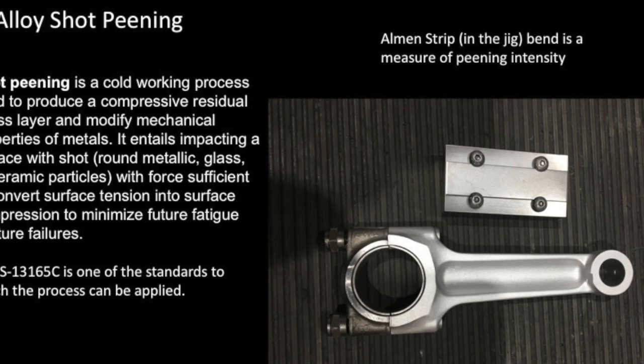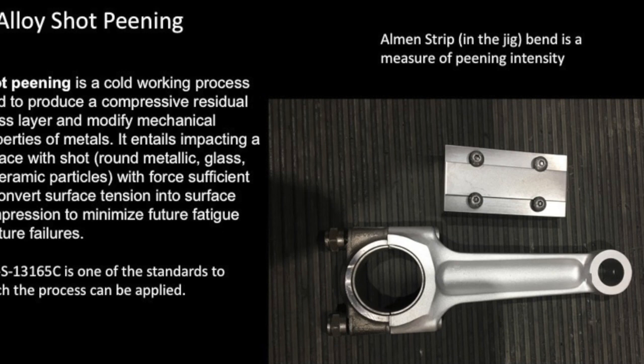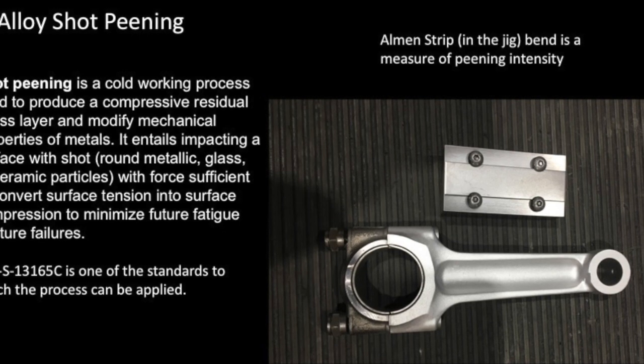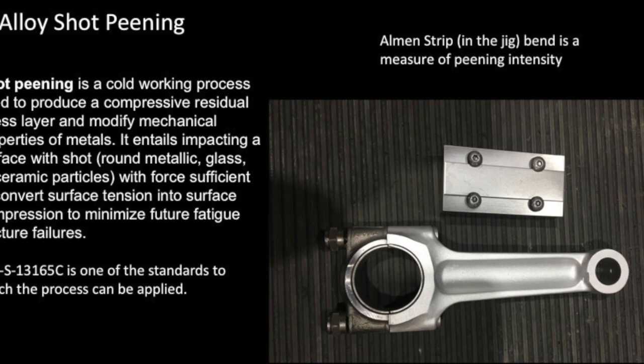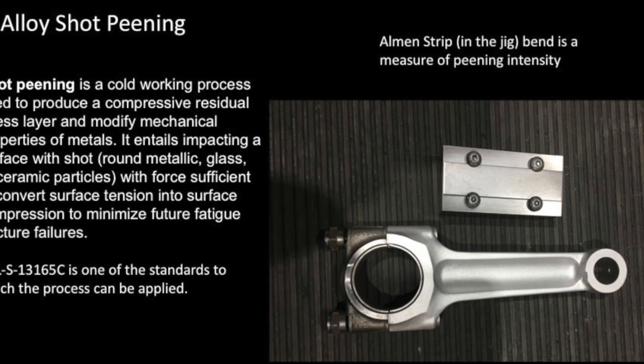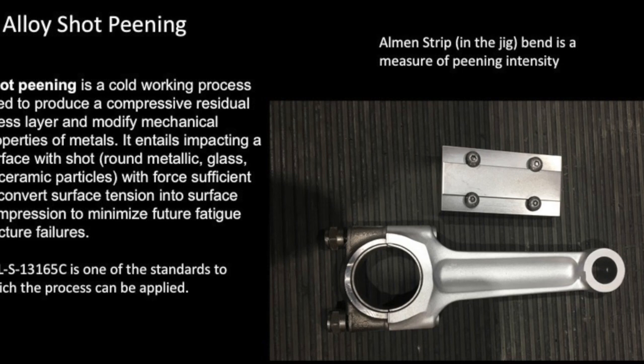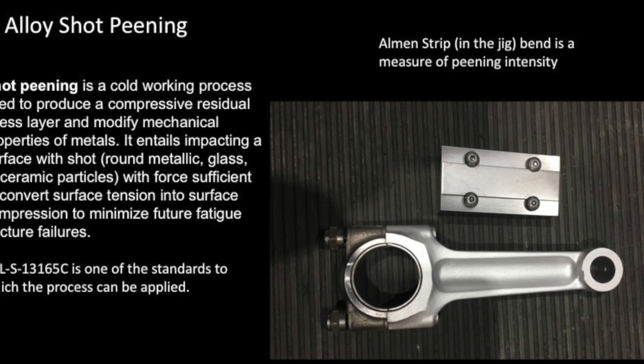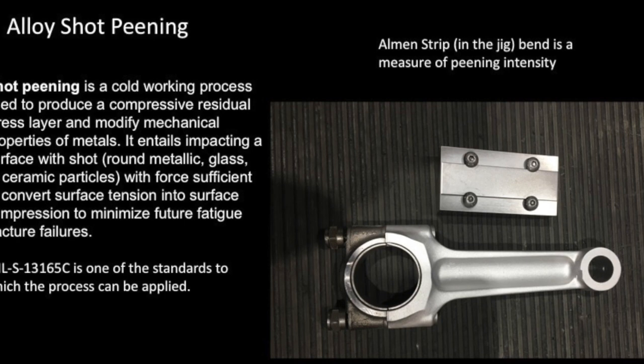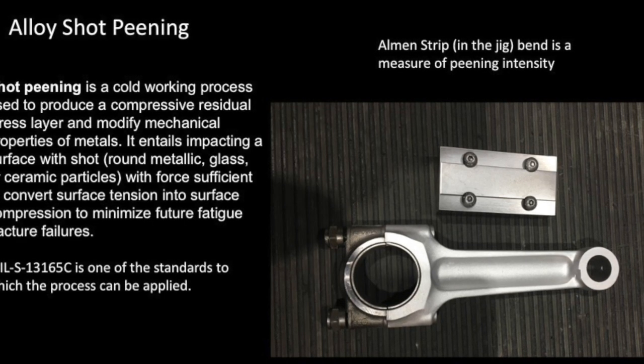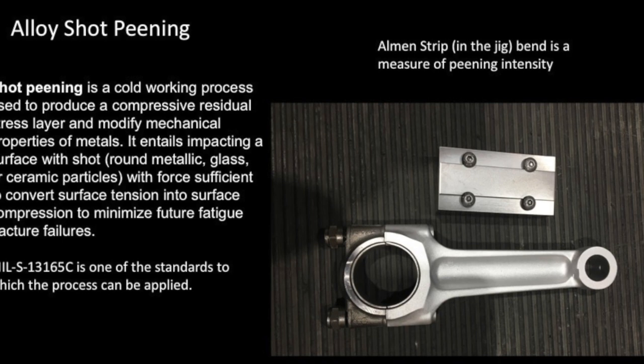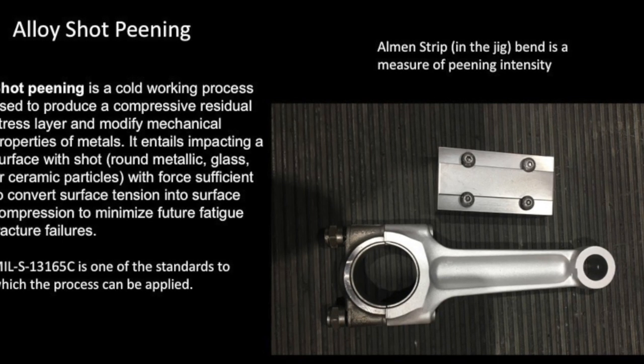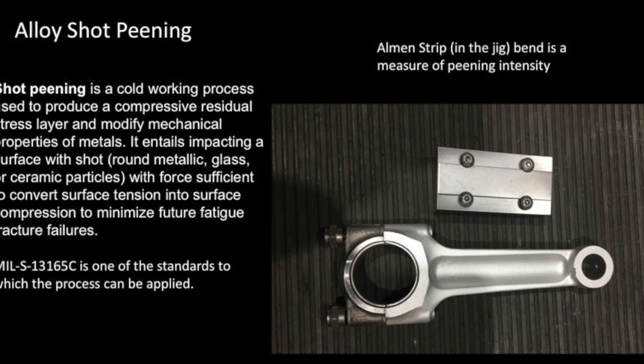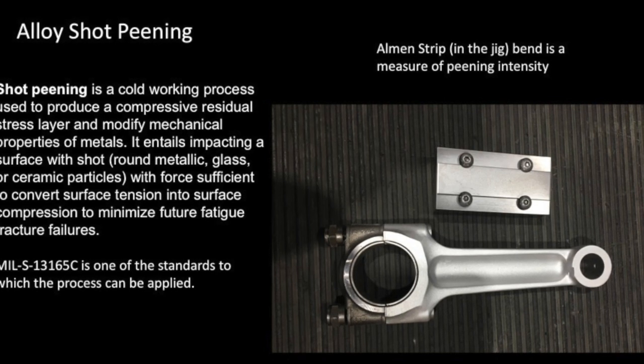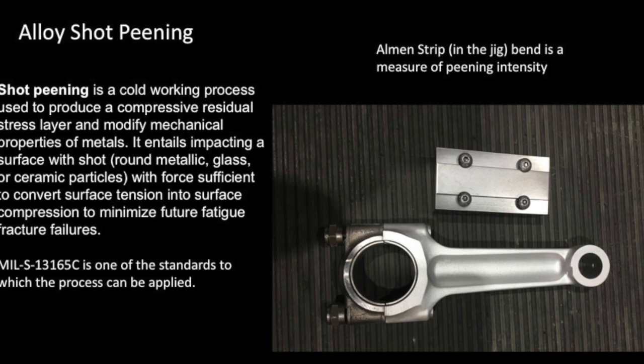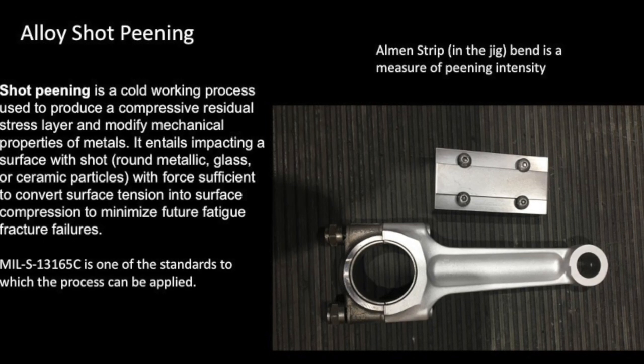So one of the issues with aluminum alloy parts is that when they're cast, the hot metal's poured into the mold, and the parts cool from the outside towards the center. Because of the differential in cooling speed between outside and inside, it quite often ends up putting the outside of the casting in tension. Any of the parts that are in tension mode are more prone to fatigue failure when they're in service. So the idea of shot peening is to actually take that tension layer on the surface of the part and convert it into a compressive layer, minimizing future possibility of fatigue fracture.